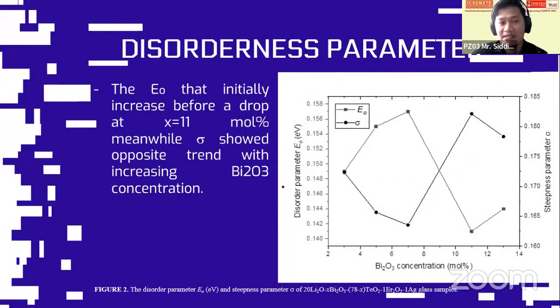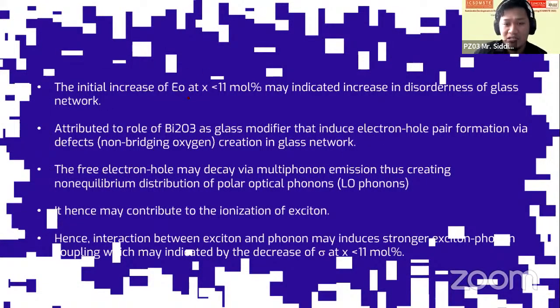And then we analyze the disorderness parameter by using the tool of our optical absorption data. We can see that the disorderness parameter is actually increasing. As you can see from here, it is increasing with the increase of bismuth before it drops. So why is it increasing? Increasing of the disorderness parameter actually indicates an increase in disorderness of the glass network. We know glass is famous for its disorderness. It is due to the role of bismuth as a glass modifier that will create defects.